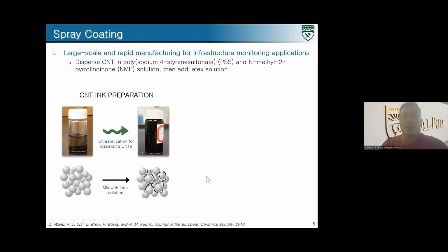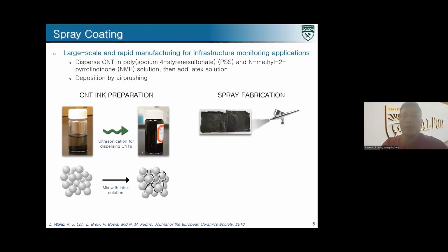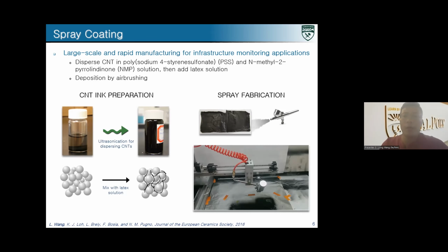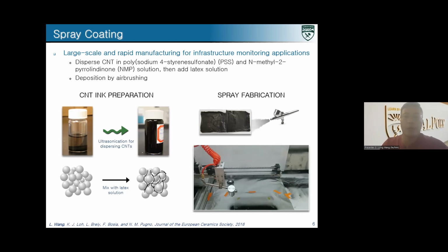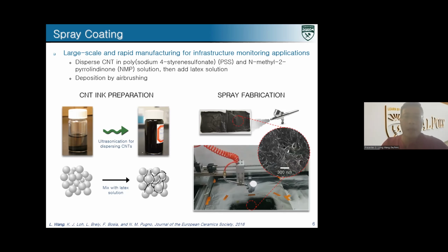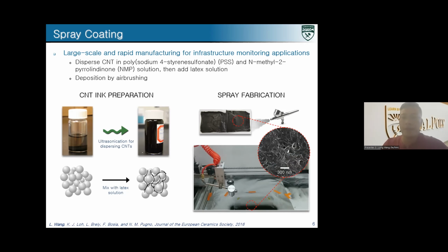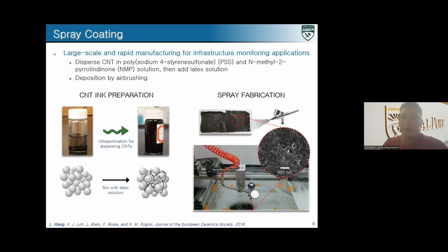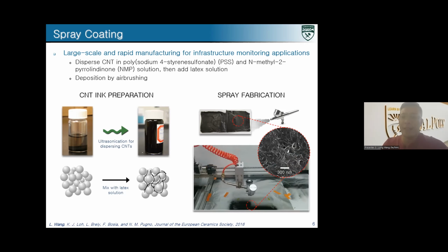In terms of the procedure, essentially I would make an ink out of, for example, the carbon nanotubes, and then we could either manually airbrush this ink onto the substrate of interest or structural surface, or we can use some sort of robotic system to more scalably spray coat this material on the structures. And this is the SEM image, scanning electron microscope image, of the microstructure of these materials. Basically, you can consider this as some sort of spaghetti dispersion inside of this material.